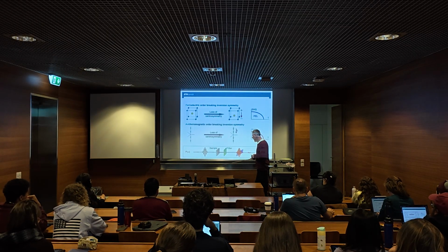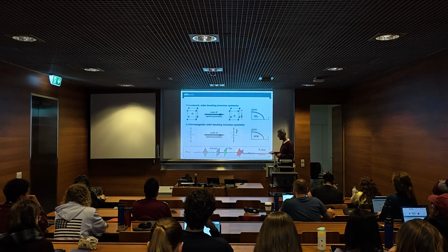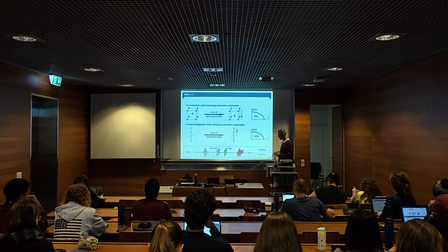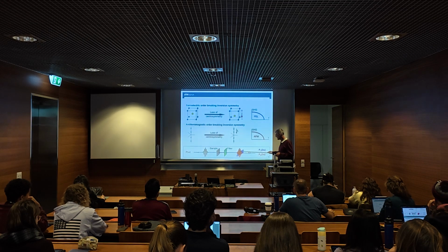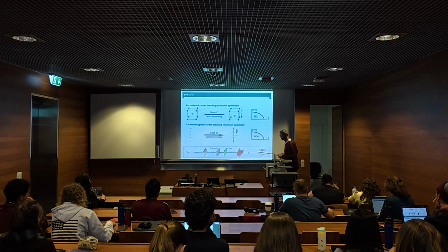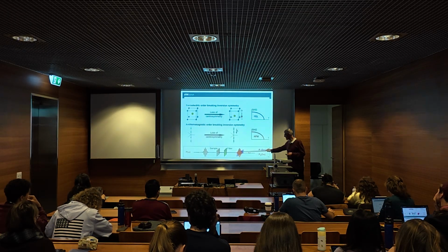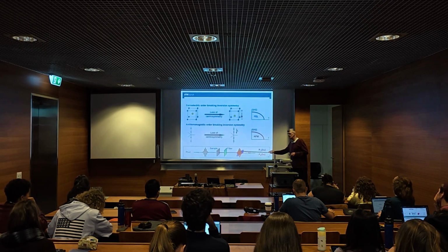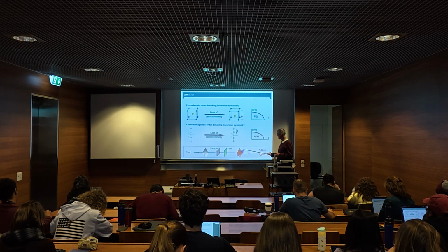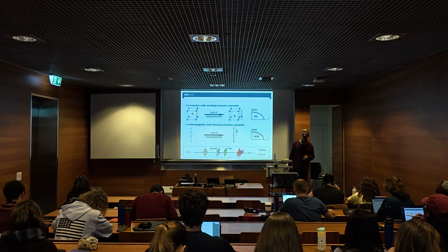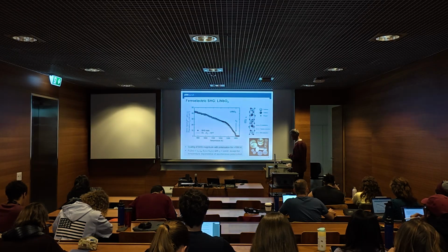So this is your experiment, this simple sketch. You send in omega light, the sample doubles it, you block the omega light, and then you analyze the frequency doubled light. Electric and magnetic order break different symmetries, and that usually corresponds to differently polarized light. So in the same sample, in the same experiment, you can even see electric and magnetic order in coexistence. Typically, the two contributions are differently polarized. So all you need is a polarization filter, and then you switch between detecting the electric or the magnetic order. That's very convenient, and it also is a very robust process.